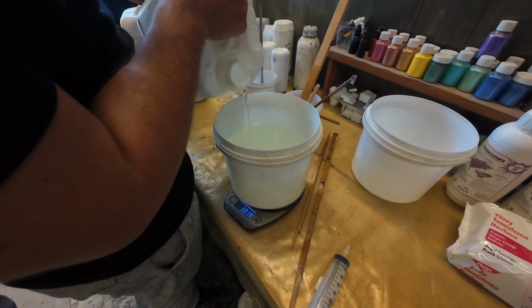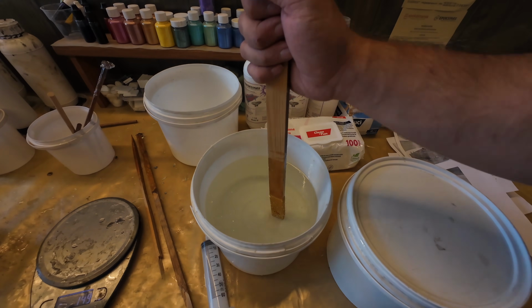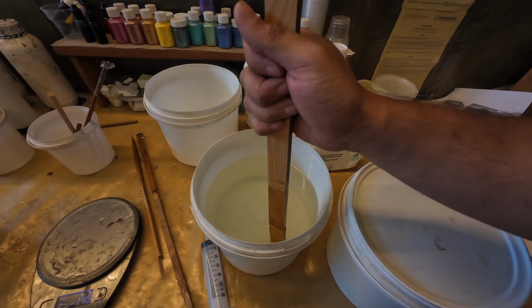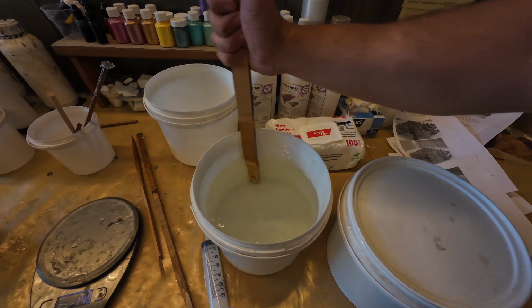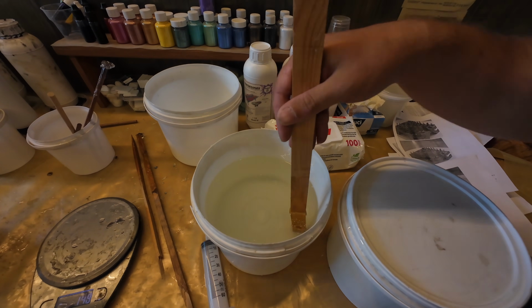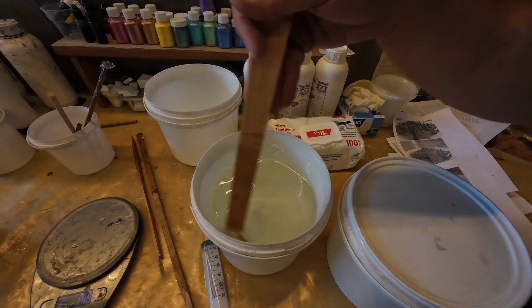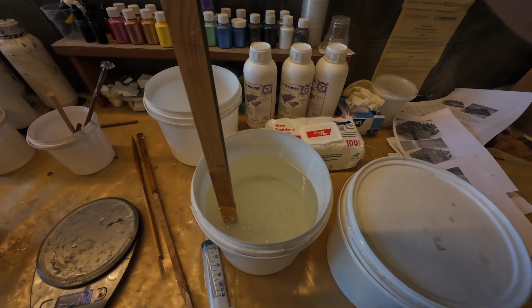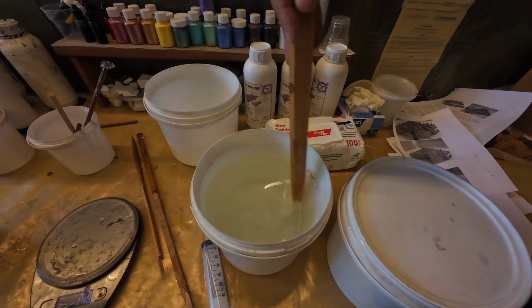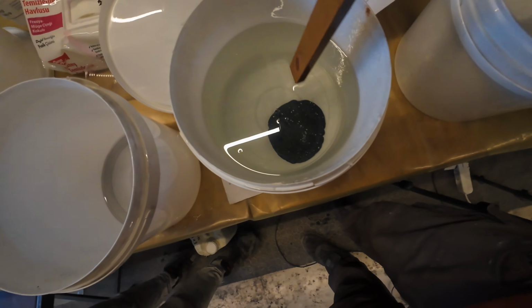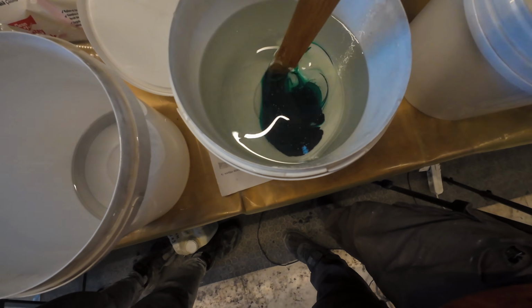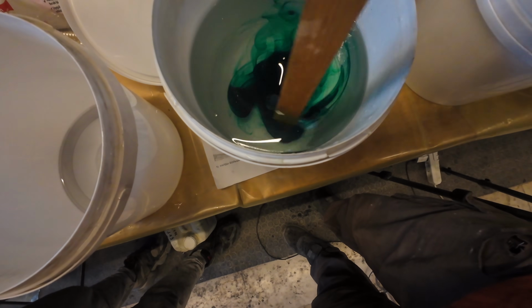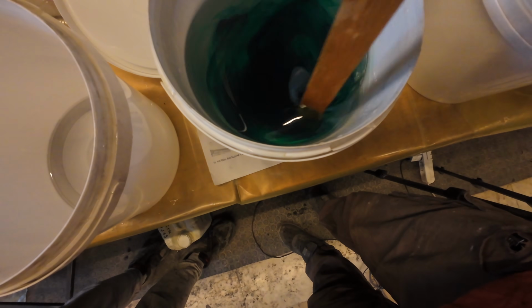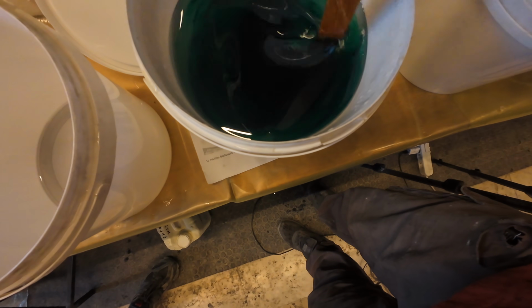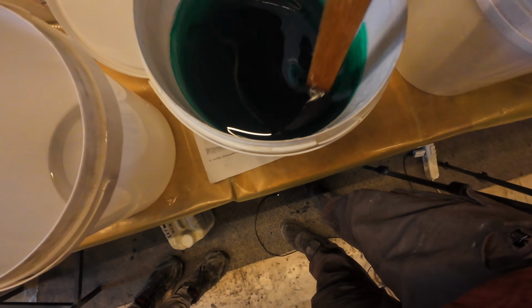Depending on the room temperature and the thickness of the pour, you can use either a medium curing resin or one that cures very slowly. For example, if the room temperature is around 18 degrees and the pour is not thicker than 2 centimeters, we use a medium resin that cures in a little more than 1 day. But if we work at a temperature close to 30 degrees, like now, we are in Antalya, and our pour is around 3 centimeters thick, we use the slowest curing resin we have. Full curing time for this resin is 4 to 6 days.